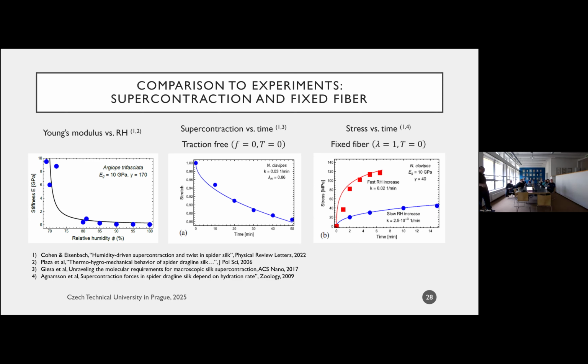Now, this is a function of time now. This is another experiment that was published in 2009. This experiment is a little more complex. What they've done here is they took a silk fiber, they constrained it on both ends, increased the relative humidity at different rates, and then they measured the stress that develops, right?